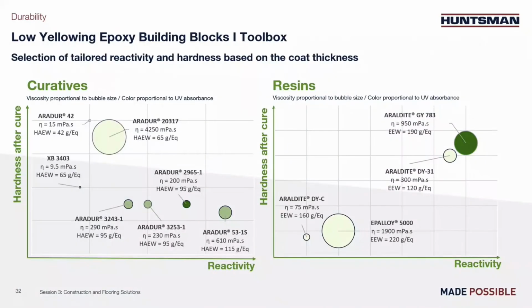So in this slide, we have gathered the building blocks which are relevant for low yellowing application. On the left side, the curative, and on the right side, the resins. Viscosity is proportional to the bubble size, and color intensity to the UV absorbance. So in effect, the deep green bubbles are standard reference, which are not especially low yellowing. In the x-axis, we have put the reactivity, and in the y-axis, the impact on hardness after cure.